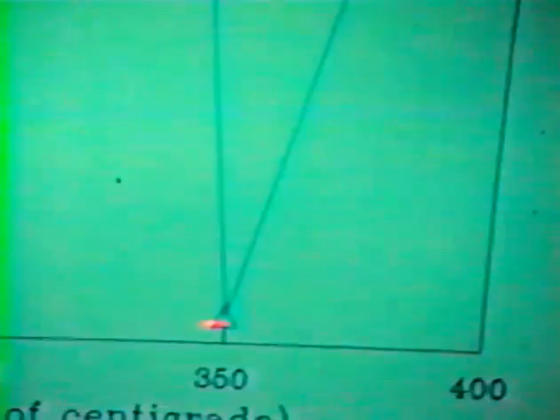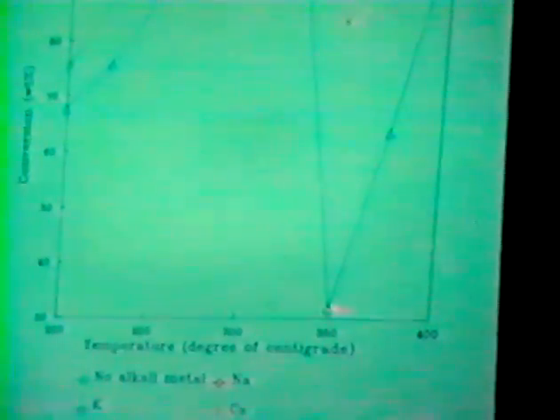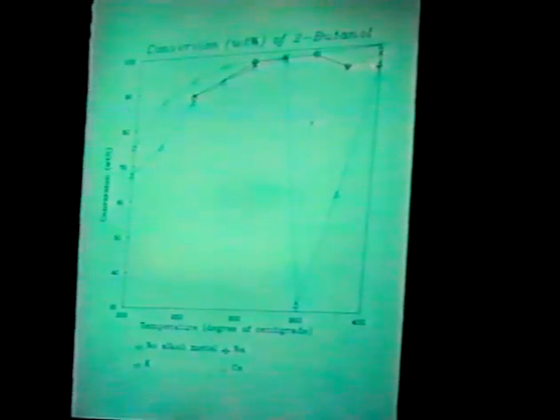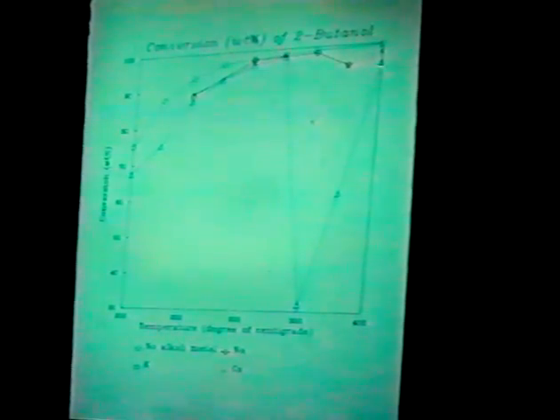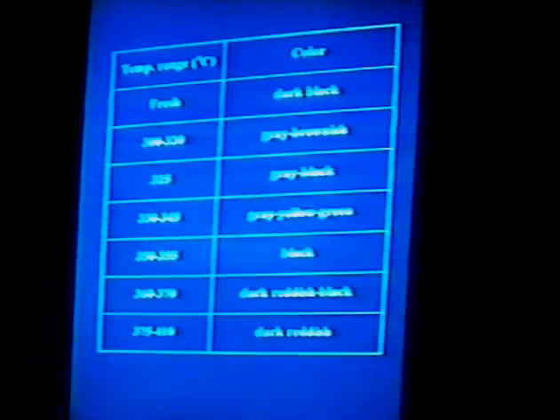the dopant of sodium, there's a loss in activity. But with cesium, little loss in activity occurs. But with potassium, you can see a drastic loss of activity. However, when the temperature goes above 350 degrees centigrade, the activity rises once again spontaneously, almost returning to the original level prevailing before the activity loss. So what happened here? Next.